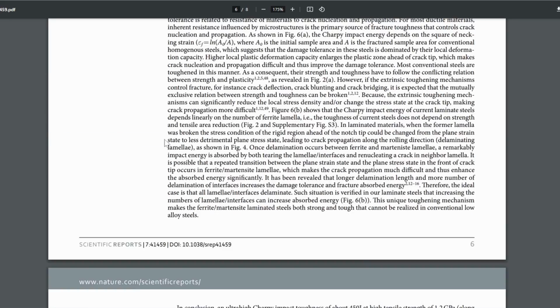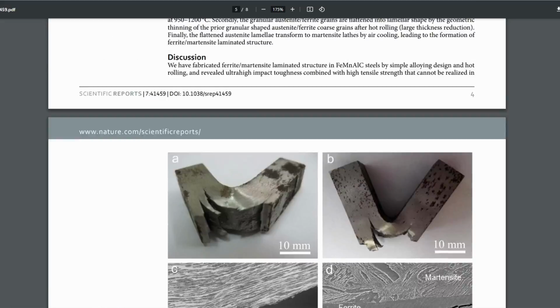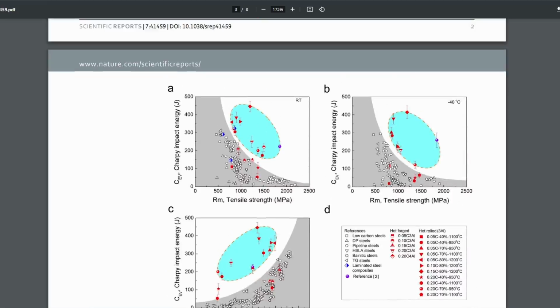The other thing he mentioned was the strength-toughness balance, which in this paper is right here. So we've got ultimate tensile strength on our x-axis. That is highly correlated with hardness. And then on our y-axis is the Charpy impact energy. And the new steels that they looked at are in this range, as high as about 1,500 megapascals. They also had one that was around 1,700, 1,800 megapascals from a reference paper. I'm not sure what that one is. And then when you've got steels that are in the 2,000 megapascal range, they are quite low in toughness compared to softer steels.